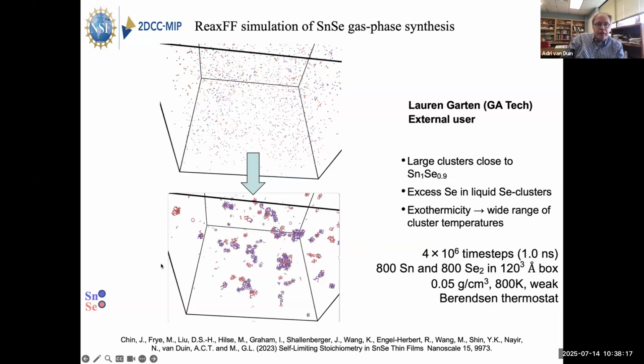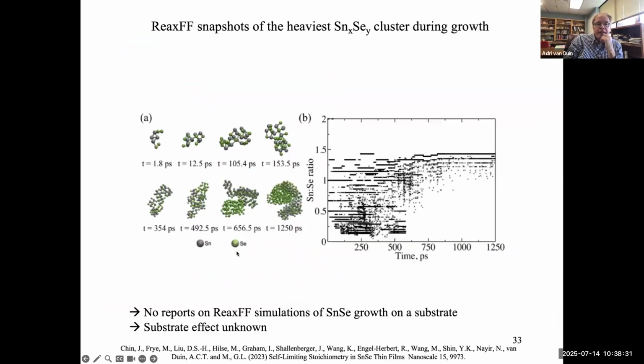We run it for about a nanosecond and we can see all these initial precursors coming out. We can also see selenium droplets. This is done at a temperature of about 800 Kelvin, so that's above the melting temperature of selenium. And we can see how those droplets kind of stick to the tin selenide.